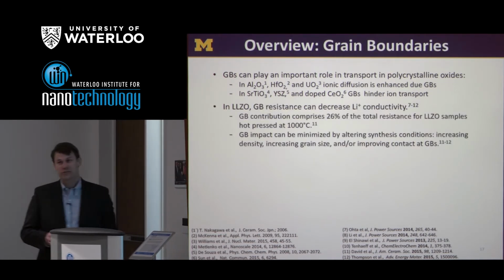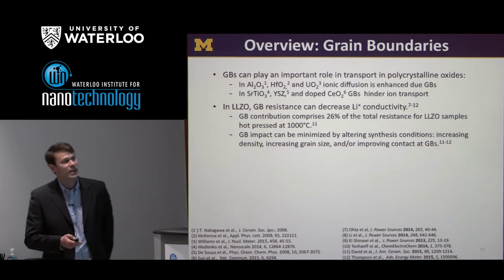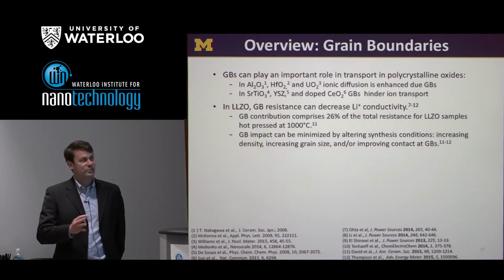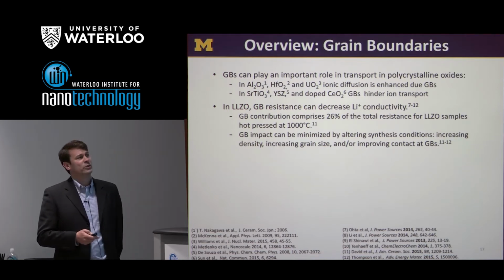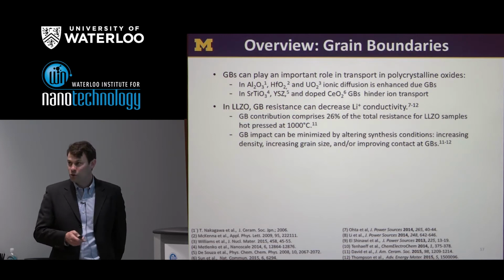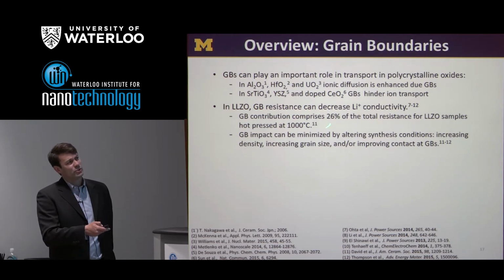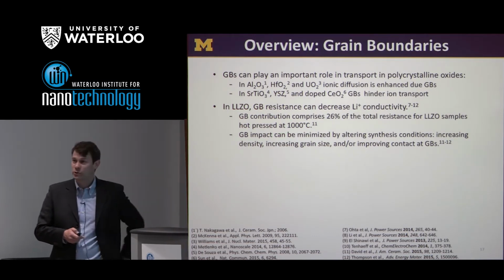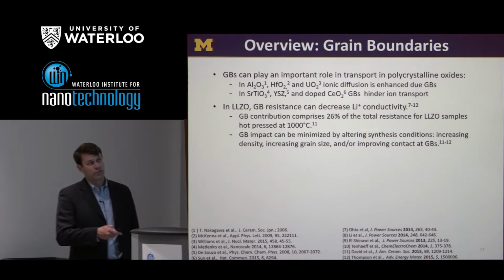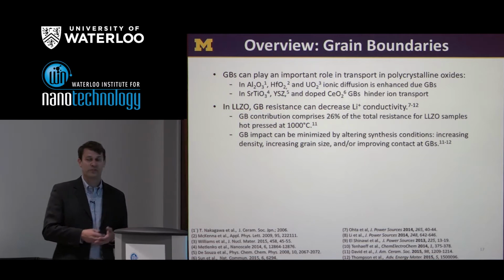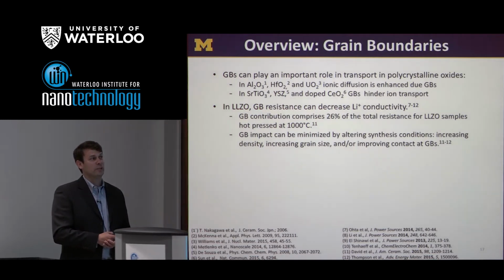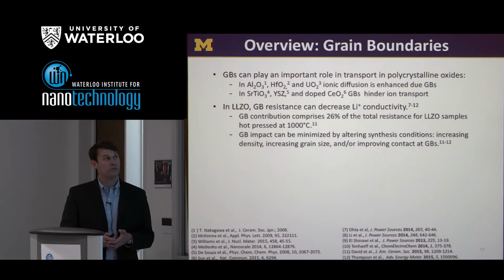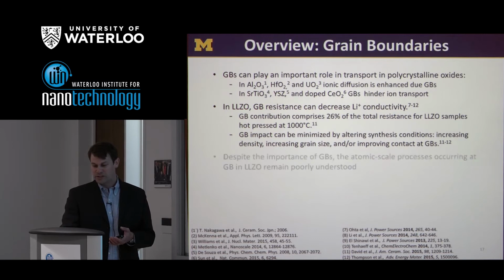In the case of LLZO, there hasn't been a ton of study so far about what effect grain boundaries have. What little has been out there seems to suggest that it's not a deal breaker, but grain boundaries do have some effect at slowing ionic transport. For example, in samples that were hot pressed at 1,000 degrees C, the grain boundary contribution is about 26%, or about a quarter of the total LLZO resistance. Of course, changing the processing conditions, for example, heating to higher temperatures or increasing the density by pressing more, would increase the grain size and reduce porosity, and those in principle could be brought to bear to improve this grain boundary resistance. I guess it's a matter of how expensive and how complicated these processing techniques are if you want to do it on a large scale.